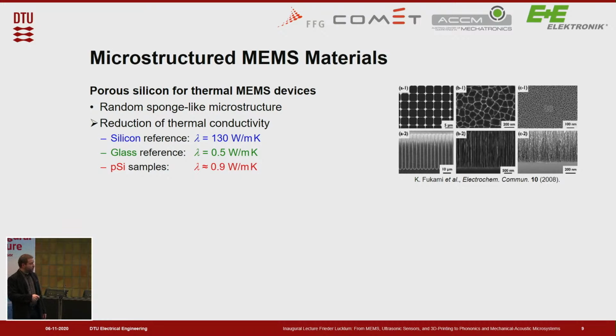And there we found what is called porous silicon. So taking a sample of silicon, single crystalline silicon, and making essentially holes in it. But not just any holes, but very tiny holes. So we are looking at holes on the order of a few 10 nanometers, the so-called mesoporous regime. Why do we need those holes on the order of 10 nanometers? Because that's the dimension that is quite similar to the mean free path of thermal phonons.